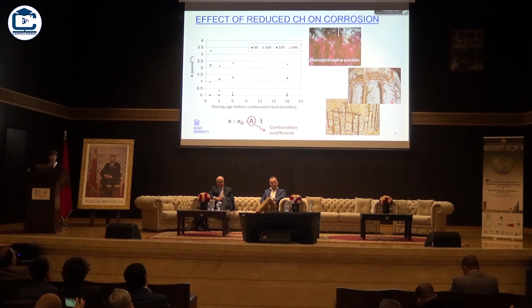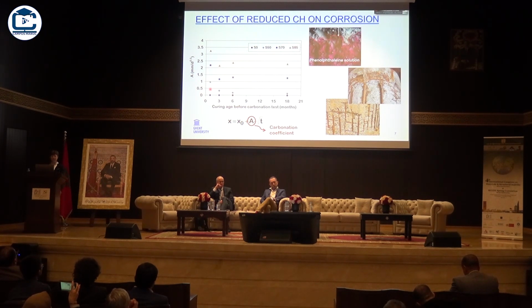However, there are many different parameters influencing this process, for instance, the curing age, and it should be said that in accelerated tests to check for carbonation, we actually concentrate all the carbon dioxide attack on the concrete at early ages. And this is at the moment, especially for mixes with pozzolanic additions, when the microstructure has not fully developed. And you can clearly see here, for instance, if you look at carbonation rates, again for concrete types with just Portland cement and then with 50, 70 and 85% of slag, if they only have been cured for 1 month and then you really submit them to an accelerated carbonation, that the carbonation rate will increase drastically with the replacement percentage. However, when you cure them longer before you apply this accelerated carbonation, the carbonation rate can actually go down a lot, and this might be more realistic if you compare it to the real situation where carbonation is more gradually going on over the service life of the concrete.